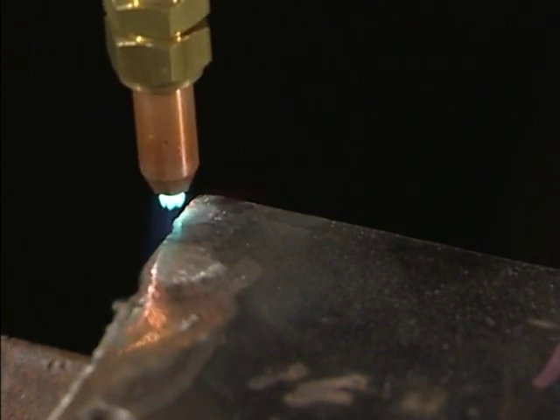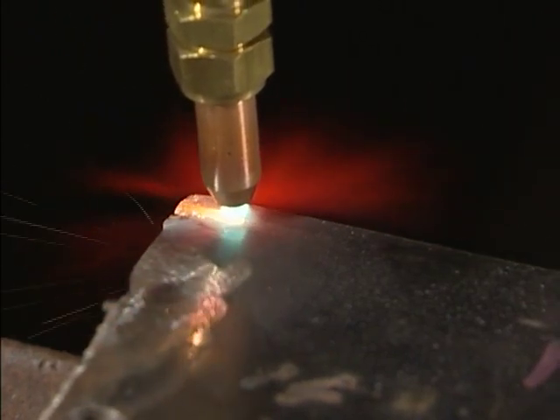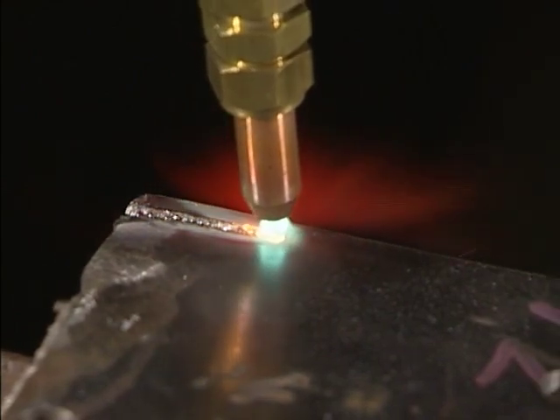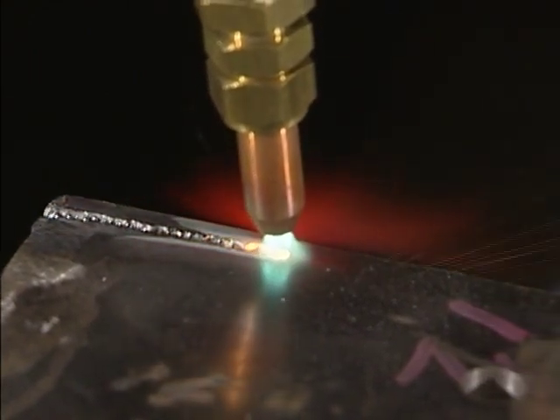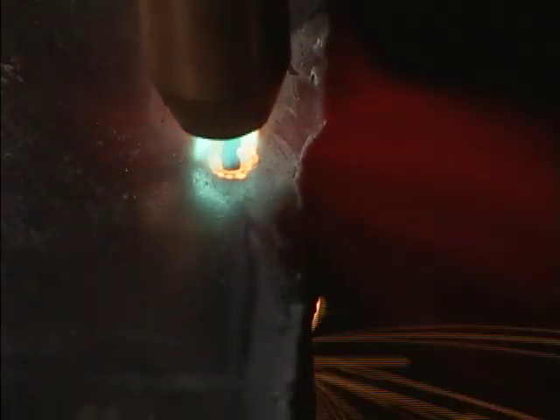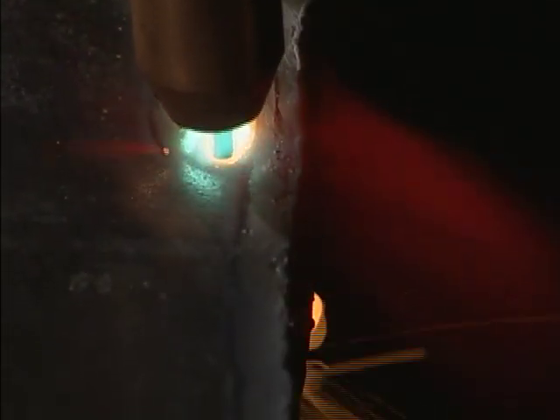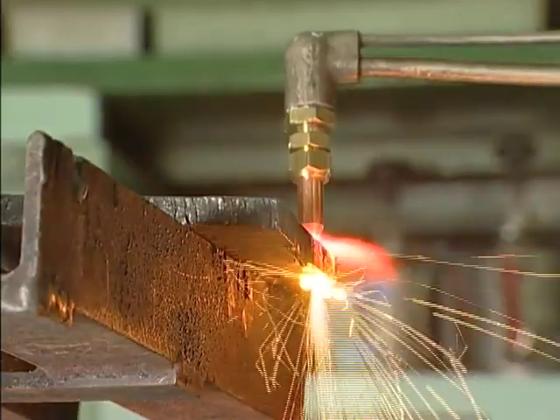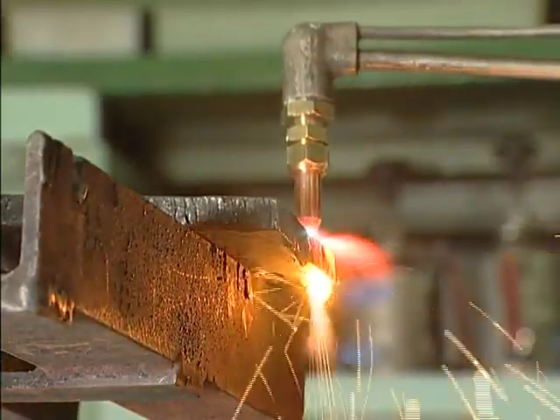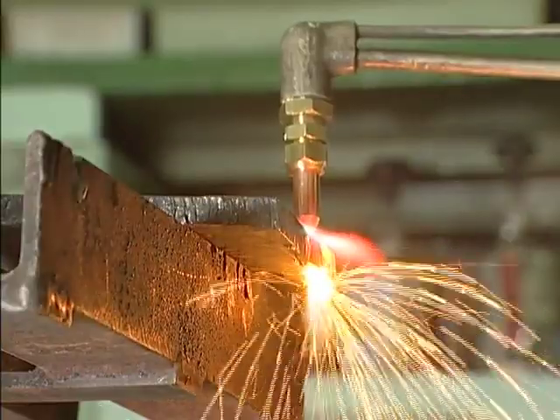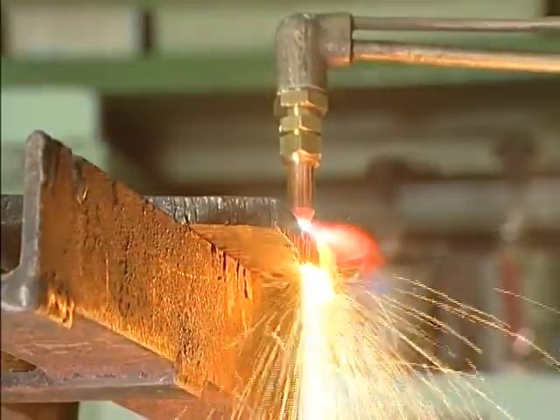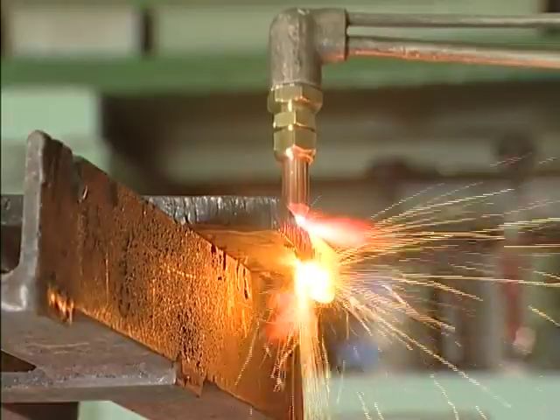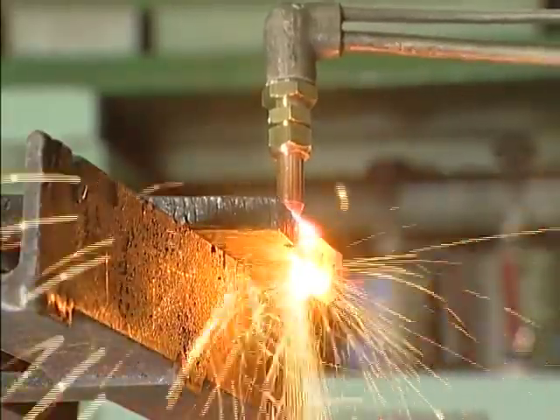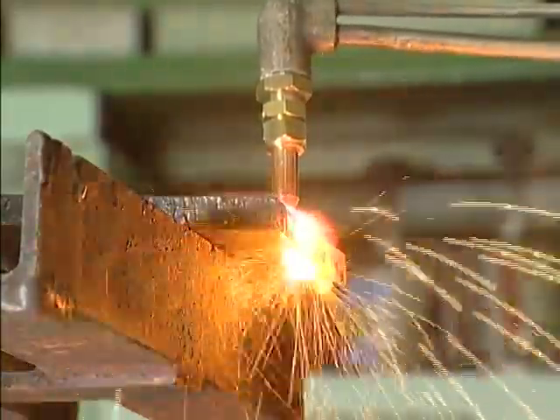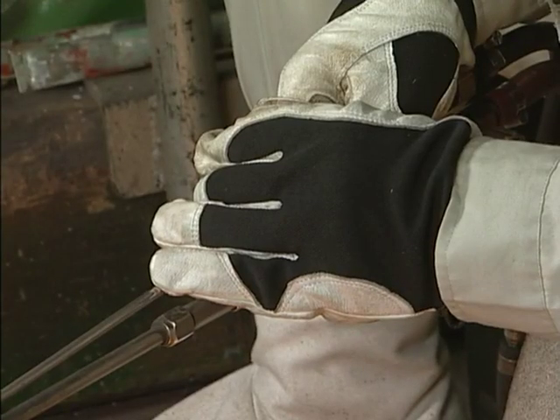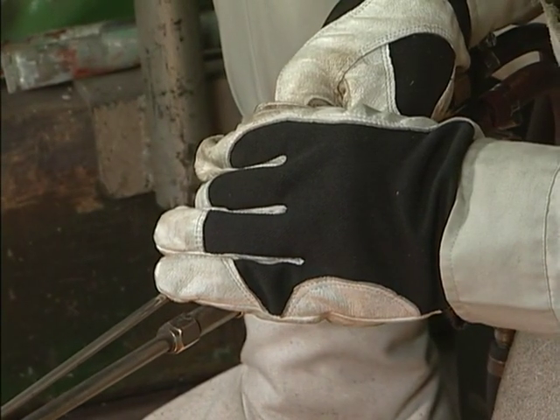Begin cutting. When dealing with a medium or thick plate, hold the cutting torch tip at a right angle to the material's surface. Also pay attention to the condition and direction of sparks emanating from the plate's bottom surface. A sudden decrease in the volume of sparks, or sparks scattering in the direction opposite the cutting direction, indicate that the cutting speed is too fast. Keep your left hand ready at all times so that you can quickly close the valve if necessary.